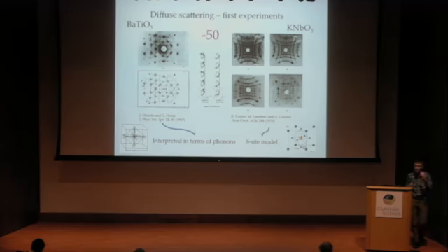And 50 years ago, there was an important extra piece of information coming to that, and it was observation of diffuse scattering, and especially these lines, which are barely seen, but they were understood in detail already, and immediately after seeing them, that has to do something with the disorder of the titanium ions and the correlation between them. Originally explained in terms of phonons, but also in terms of the eight-site model, and especially it was the observation in potassium niobate when the results were much more clear, the diffuse scattering was much stronger, and this group, Comes, Lambert and Guinier, could see actually in different phases how these sheets of diffuse scattering are gradually disappearing, and in the low temperature phase, rhombohedral one, they are not.